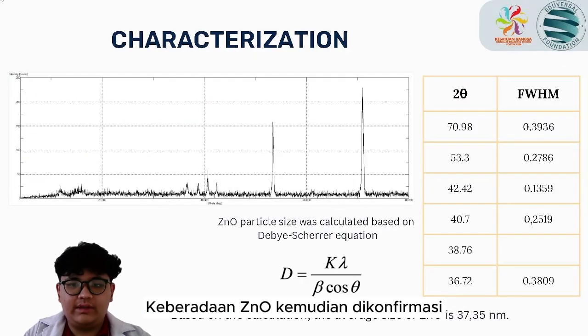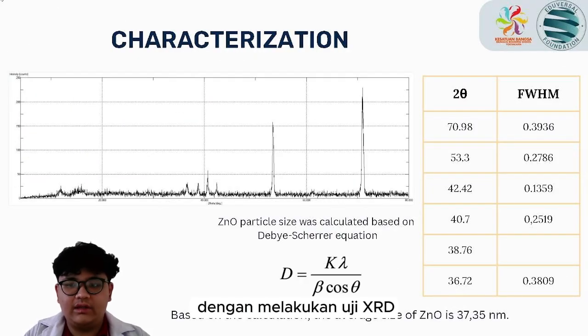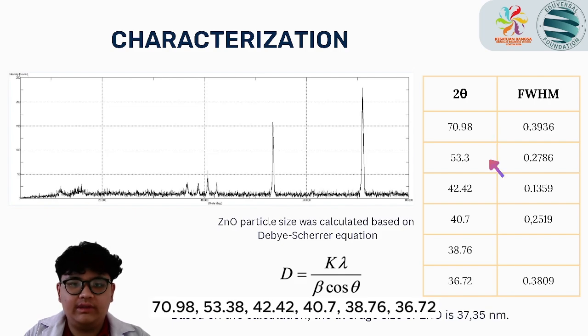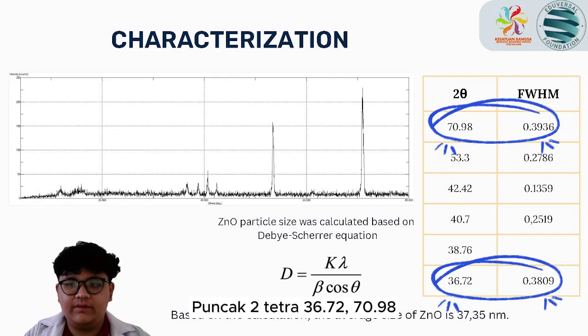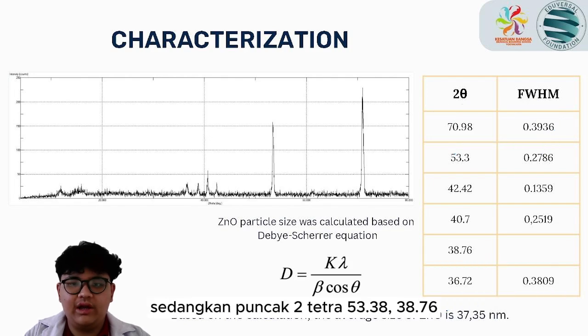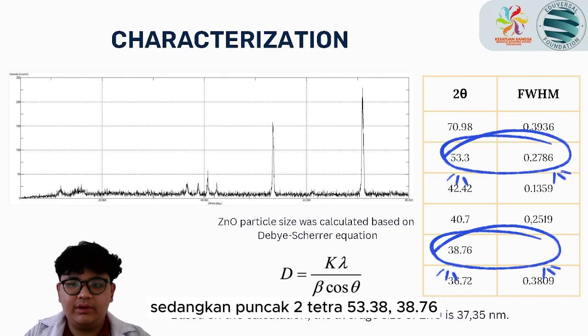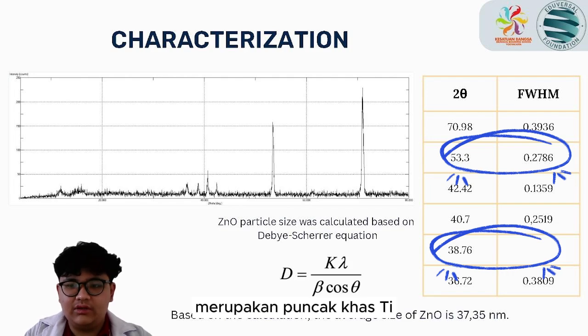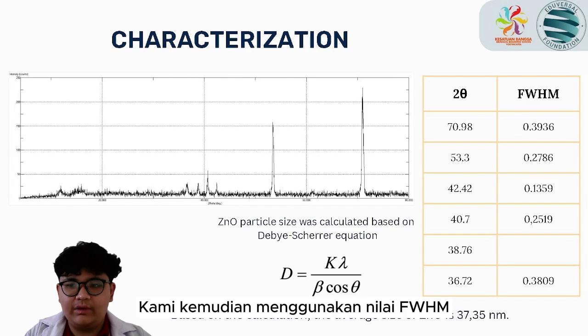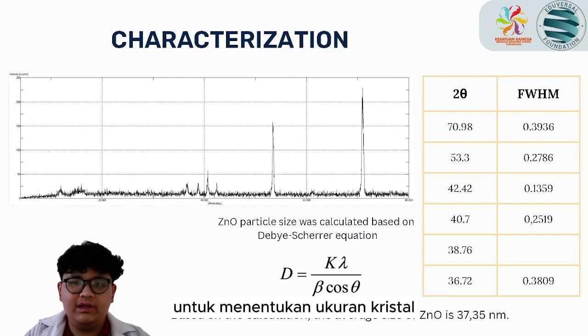The presence of zinc oxide was then confirmed by conducting XRD tests, obtaining 6 peaks at 2 theta: 70.98, 53.38, 42.42, 40.7, 38.76, 36.72. Peaks at 2 theta 36.72 and 70.98 indicate the presence of zinc oxide, while the peaks at 2 theta 53.38 and 38.76 are typical titanium peaks. We then use the FWHM value of each peak to determine the crystal size.